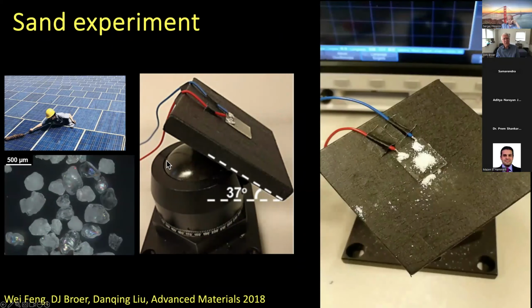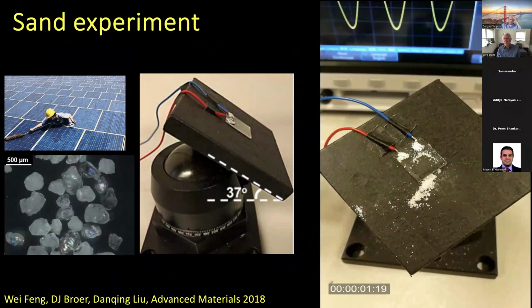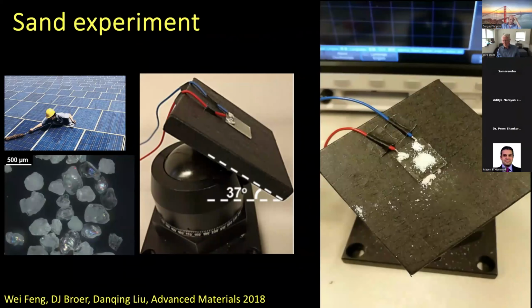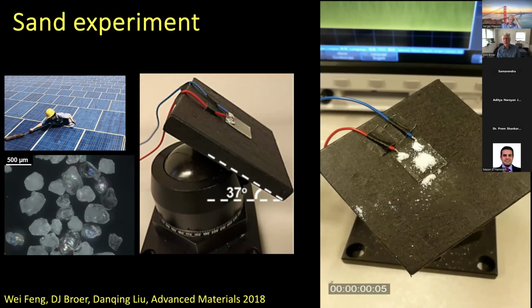So this is the sample that we have here. We brought some sand on it, model sand in this case, and we start actuating. So this is the sand. On the monitor you can see the moment of actuation, and as soon as it's actuated, the sand is removed. Basically, we have the two effects here. We have the high frequency modulation we saw just before, and we have the surface inversion. So we have a two-step mechanism for the removal of the sand.